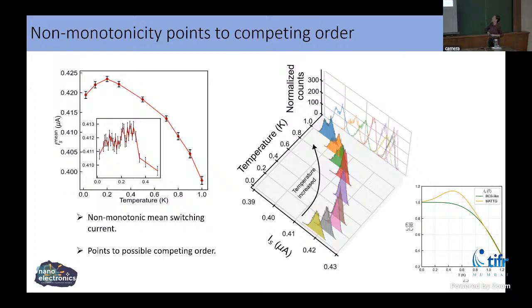So a possible reason why we see this upturn is because there exists a competing order. Now, what is this competing order actually doing? In the ground state, there is a competing order and there is a superconducting order. Now, in the initial stages, when I am increasing the temperature, the superconducting order actually strengthens at the cost of this competing order weakening. That I see as an enhancement of critical current. Now, beyond this particular temperature, when the competition is less strong, the superconductor acts like it would have, and the critical current monotonically decreases with temperature.